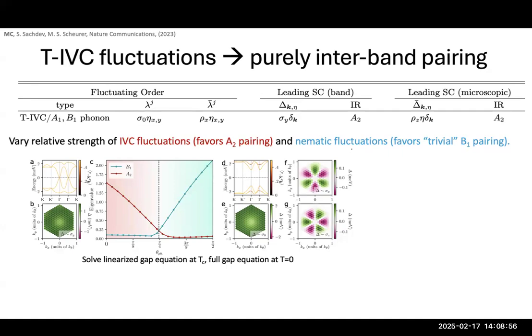So if I take this data point here for the B1 pairing, and I take this data point here for the A2 pairing, here I'm plotting the order parameter. This is the sigma naught component of the pairing for the intraband pairing and for the interband pairing, and they're roughly of the same order. But if I look at the excitation spectrum, what I see for the intraband pairing is that it's fully gapped, and the gap is roughly of the same order as this order parameter. But for the interband pairing state, even though the order parameter is large relative to the bandwidth, this state is just beginning to become fully gapped.